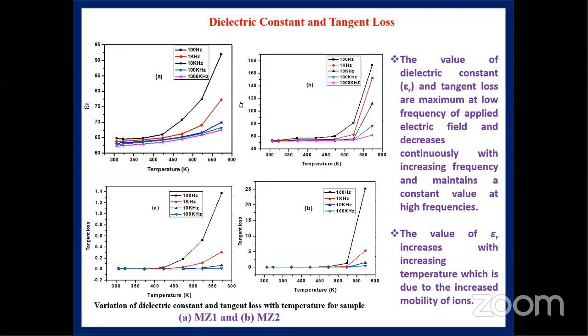Again, we performed the electrical properties of these two different ratios of the nanocomposite. You can see the figure, the variation of dielectric constant and dielectric loss with different temperatures and different frequencies. The values of dielectric constant and dielectric loss are maximum at low frequency and decrease continuously with increasing frequency. They maintain a constant value at higher frequencies. Then the value of dielectric constant increases with increasing temperature, which is due to the increase in the mobility of ions.